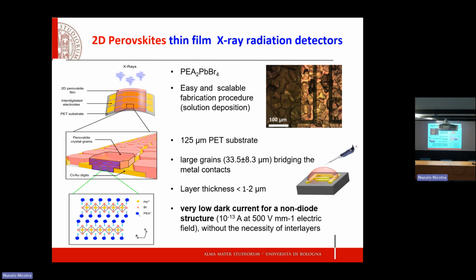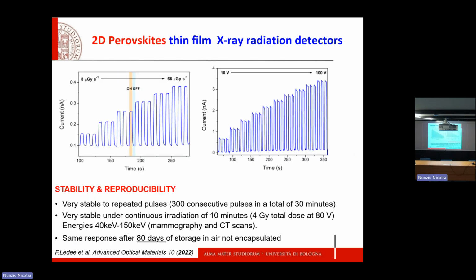It means the transport only can happen since it is a 2D material, has a very high directionality. And this reduces the dark current, so the current that you collect without doing anything to your material. And the result is that you have a very, very good detector because you're starting from a material that is basically showing an almost zero current.